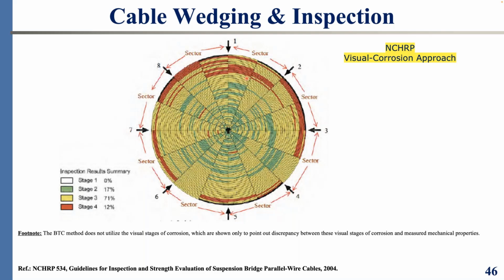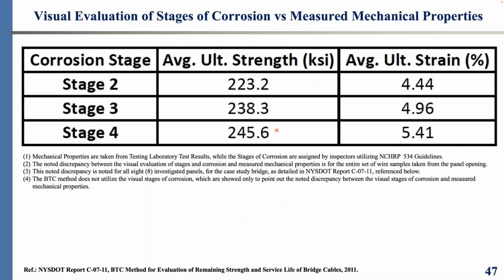So what gives? Well, actually, this visual evaluation of stages of corrosion is juxtaposed here versus the measured mechanical properties. This is actually referenced in New York State DOT report C0711, where the mechanical properties are taken from the testing laboratory, and all these stages of corrosion defined by the folks that did the NCHRP. For that case study, we did the cable strength by the BTC method, and other folks did the NCHRP methodology, and we are just juxtaposing that to show the kind of discrepancy. One would expect stage 4 to be weaker than stage 3 and stage 2. It is flipped upside down.